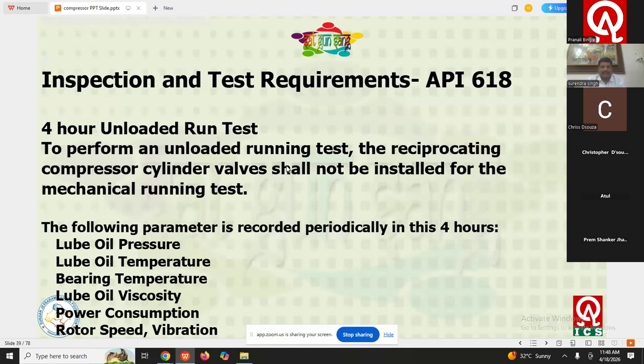Now, coming to the 4 hour unloaded run test, which needs to be performed in line with API 618. During this 4 hour unloaded run test, we need to monitor the lube oil pressure, lube oil temperature, bearing temperature, lube oil viscosity, power consumption, rotor speed, and vibration, and all the parameters must be within the limits defined either in the client procedure or in the QP.